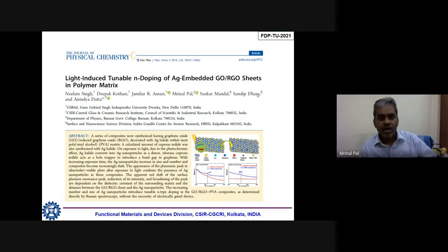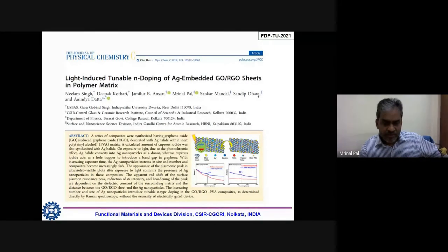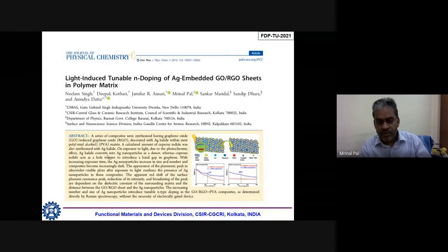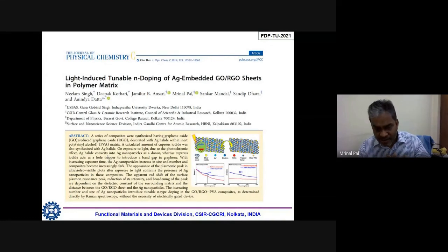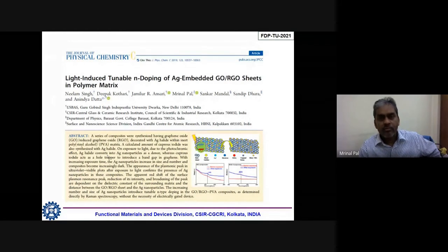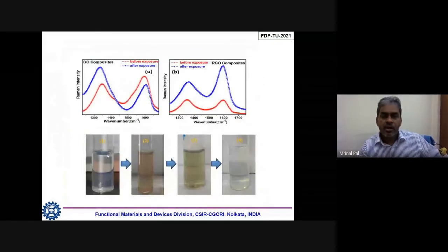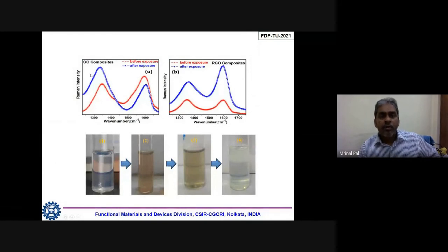This is another work, which is light-induced tunable silver doping on graphene RGO sheets. In this case, we have used one polymer matrix, and we have shown that by illuminating with ordinary light, it is possible to deposit more and more silver nanoparticles, and by depositing that, it is possible to tune the luminescence property and the band gap also. Everything is possible. You see, these are the optical properties, and you see after exposure this is blue, and in this case this is for graphene oxide.